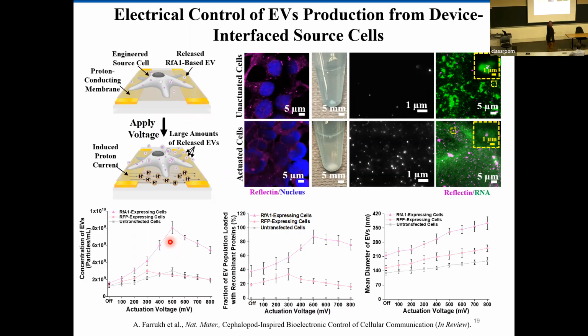With these techniques, we can see that when we apply a bias between 100 to 800 millivolts, we have a peak production of reflectin containing extracellular vesicles at 500 millivolts. We also see a peak packaging of the reflectin protein at 500 millivolts, with more than 80% packaging of the protein in our vesicles. Finally, we also have some control over the size of the vesicles, which increases with the bias, because the more you destabilize the cell membrane with the pH outside the cell, the more it tries to get rid of it by making these reflectin containing particles.